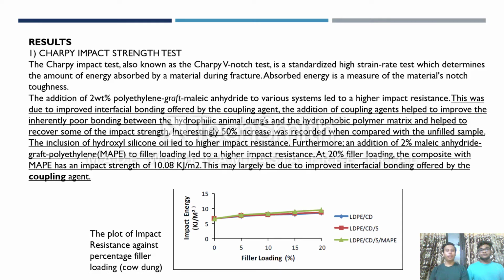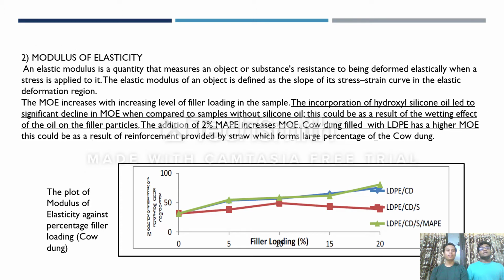At 20% filler loading, the composite with MAPE has an impact strength of 10.08 kJ per meter square. This may largely be due to the improved interfacial bonding offered by the coupling agent, that is MAPE, as you can see in the graph. Second, the result was based on modulus of elasticity.